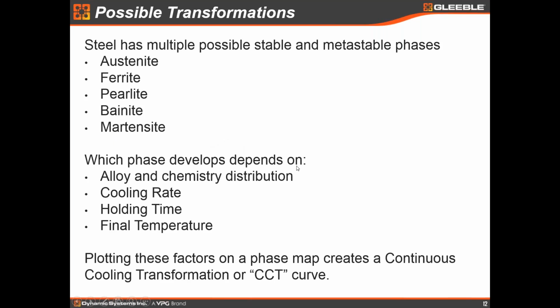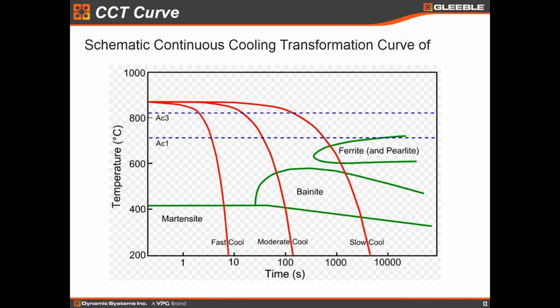And which of those phases depends on, of course, the alloy and chemistry distribution of the alloy in that part, but largely depending on cooling rate, holding time, and the final temperature that we quench to. So it becomes a very big challenge, I guess, in the steel industry to develop these process maps which show which of these phases will develop under different holding times, different cooling rates, different processing parameters. So if we plot all those onto one curve, we get what we call a continuous cooling transformation curve.